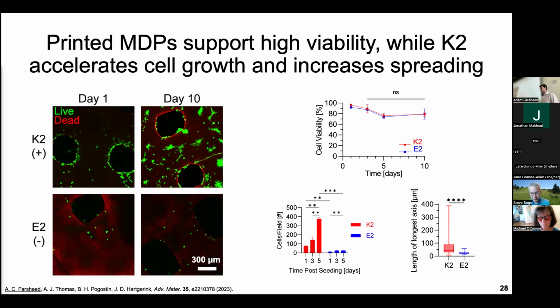And the third thing that you might notice in the far right image, comparing the 2 right images, is the cells on the positively charged material are kind of all spread out, whereas those on the E2 negatively charged material are kind of bundled up. And to very quickly tell you why we think that's the case, we think it's actually an electrostatic interaction between the negatively charged membranes of the cells. And so they're naturally pulled onto our positively charged material and feel pushed on our negatively charged material. And this is also seen in a lot of cell culture applications where we might use poly D-lysine coated plates. Well, K2 is a poly D-lysine mimic, if you want to say that.